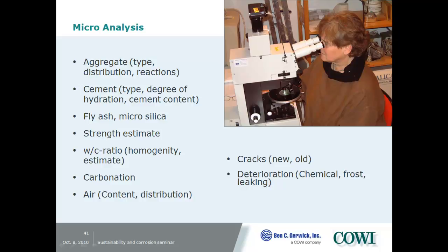So how do you distinguish between them? We distinguish between them by where the crack is running. If you have cracks that run through aggregates, it's formed in the hardened phase. If it only goes in the cement paste, it's an early age crack.